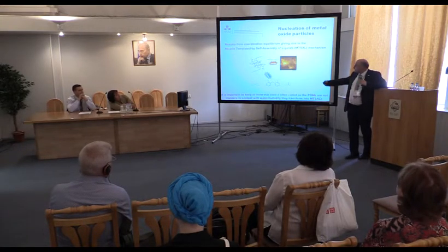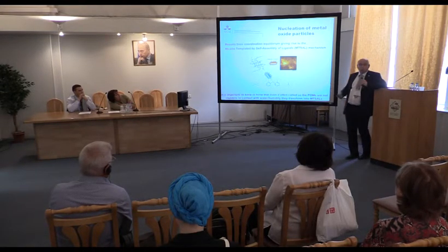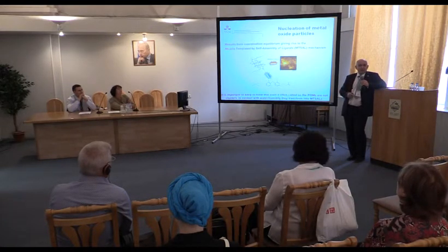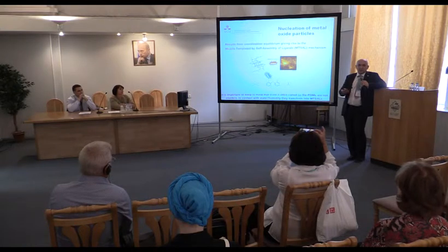But they are not. So the problem is, here you see an AFM image. If we take these so-called clusters and add more water, what will happen? They will transform into these primary particles of sol-gels. So from the size below 1 nanometer, they will immediately grow to above 3 nanometers and will have an anatase structure. And of course, in X-ray, you will not see the pattern in this case, but if you use other techniques which are sensitive to structure, EXAFS, for example, or electron diffraction, you will see that it is anatase.